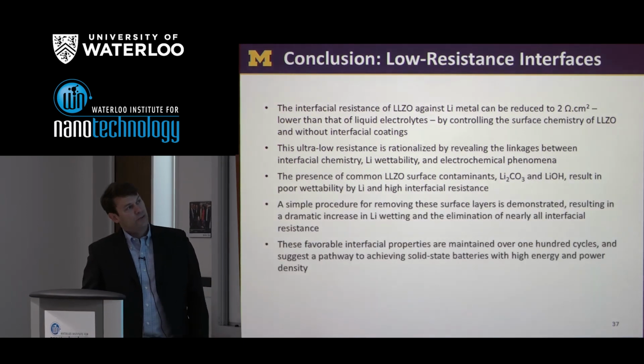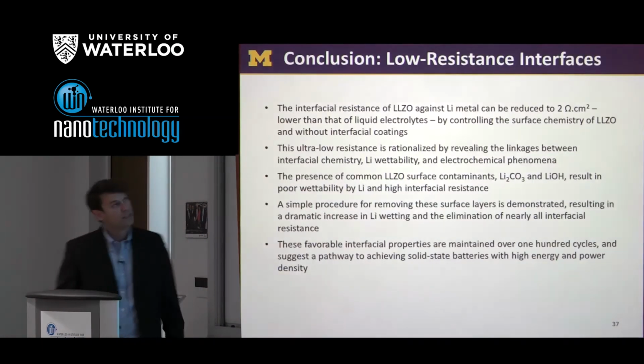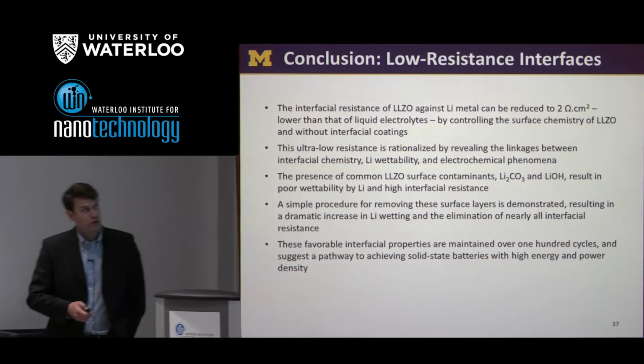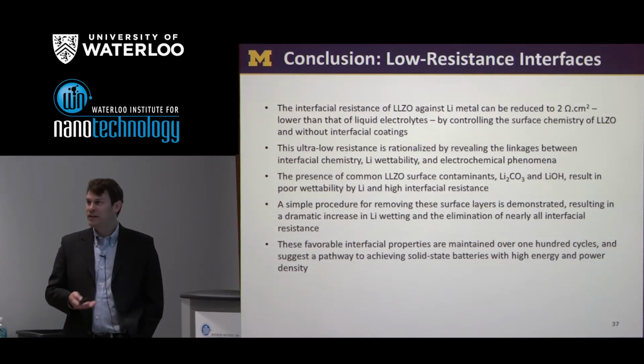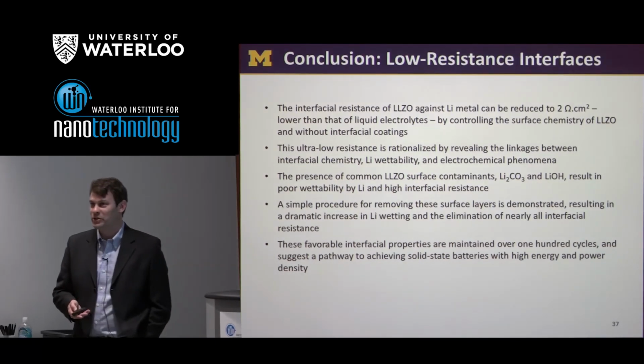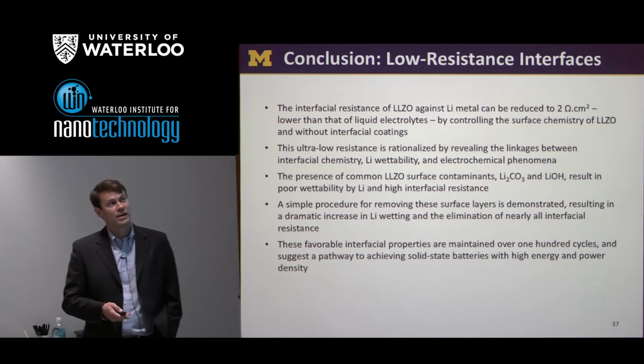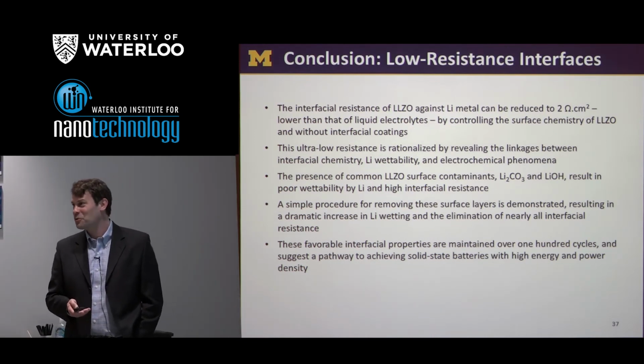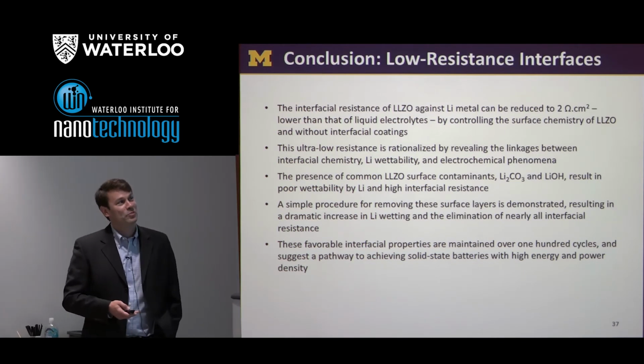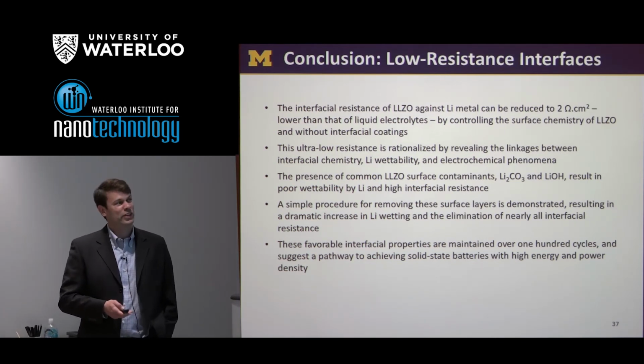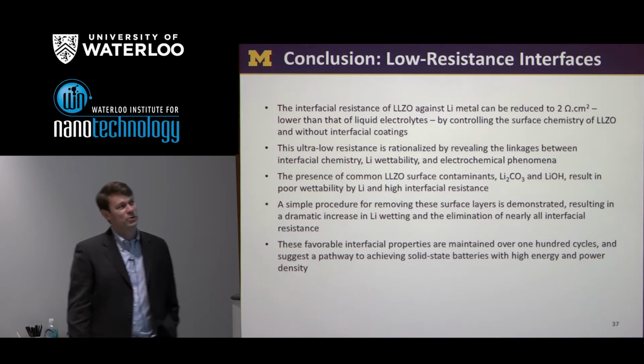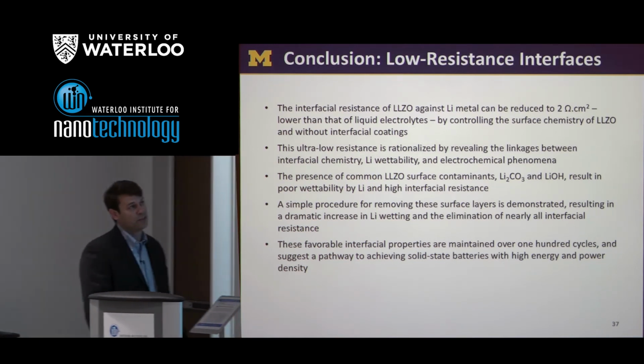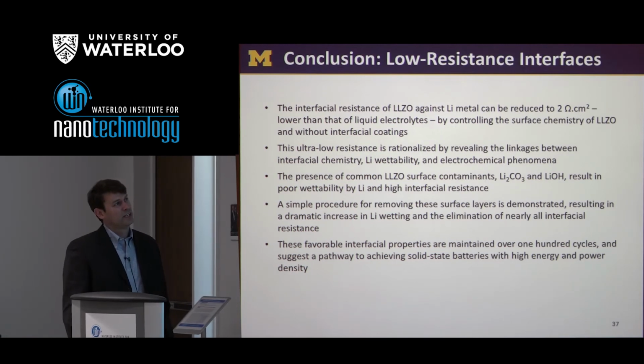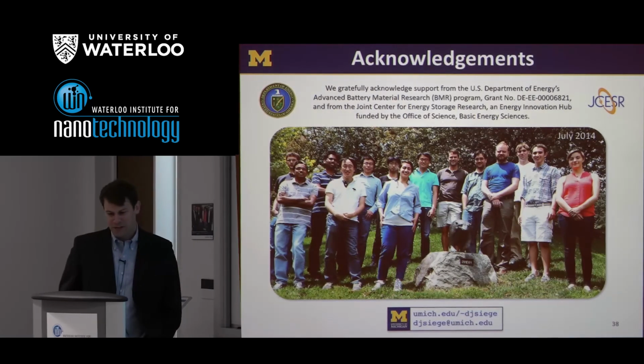So this is my last summary slide. The notion here is that it is possible to make very nice interfaces between LLZO and lithium metal with rather low resistance, following what the experimentalists call a straightforward cleaning procedure without the need for coatings. This correlates with lithium wettability and was also assessed using the electrochemical phenomena, or the impedance spectra, that we also discussed. That's all. So let me stop here.